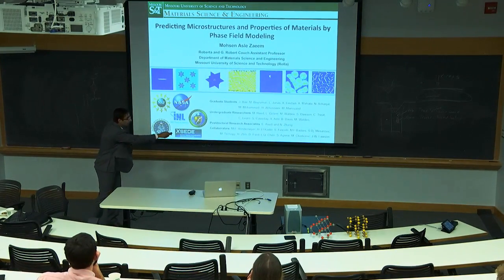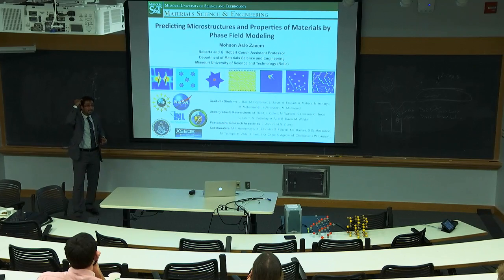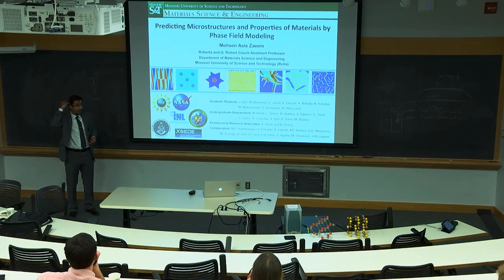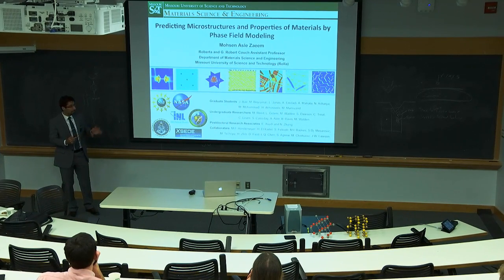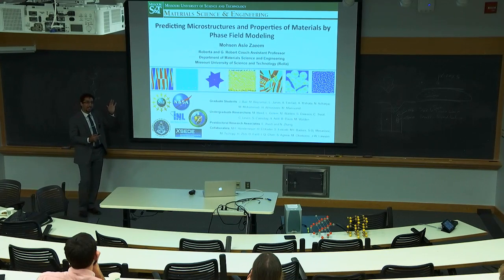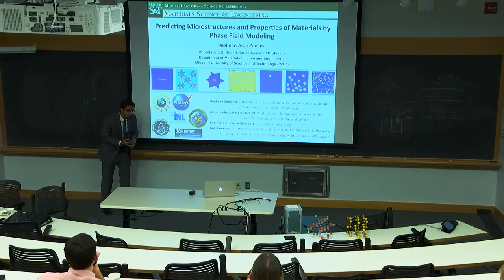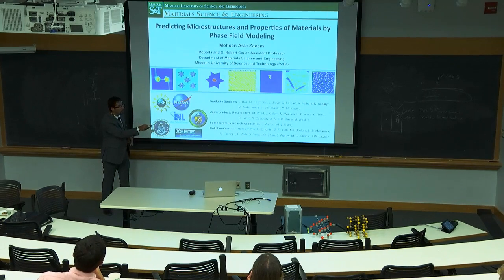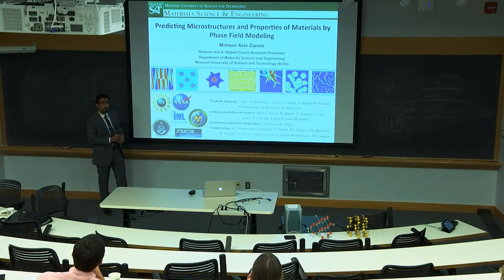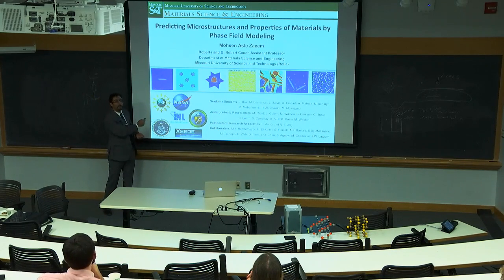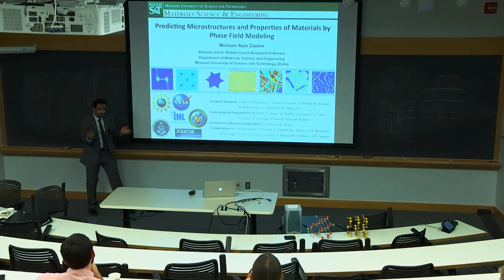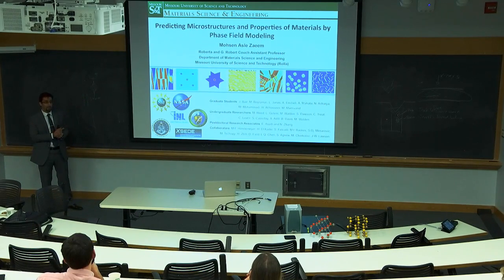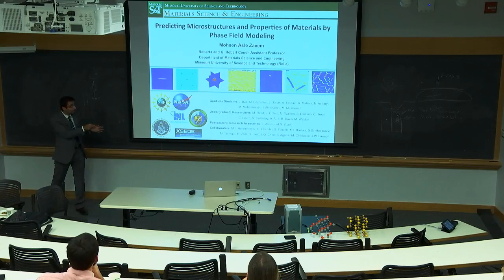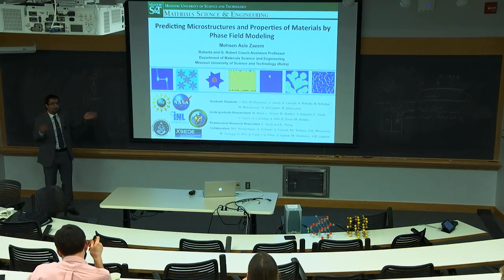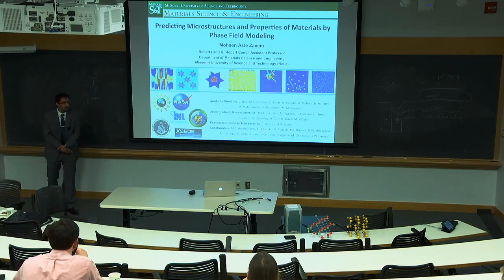For example, this one is a crystallization of a semi-crystalline polymer. How different is this model than this one? That is the question, right? It's basically not that different. The interface properties, the formation energies, and the interface anisotropy will produce this kind of crystalline structure. For the semi-crystalline polymers, this is the magnesium, by the way. So the phase field model could be extended to even completely different types of materials. But if you go to molecular dynamics, it's not. You need different interatomic potentials. The mechanisms are completely different.